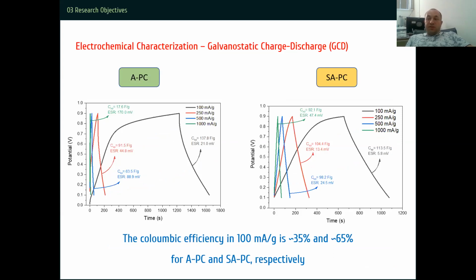In order to determine the specific capacitance, we conducted constant current charge discharge test. Then we calculated the specific capacitance in farads per gram. The specific capacitance at 100 milliamps per gram current density for APC sample is higher than SAPC sample. However, the Coulombic efficiency, which is very important to determine the workability of a cell, a supercapacitor, at 100 milliamps per gram is almost 35% and 65% for APC and SAPC sample respectively.